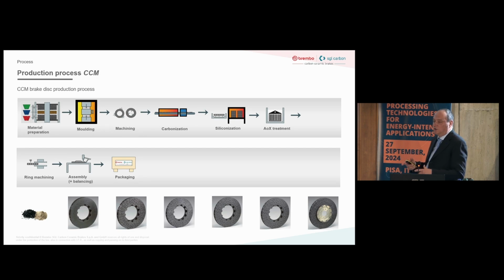So each type of rotor has the recipe for molding. Then after molding and easy machining, just making the holes, and then carbonization to transform phenolic resin into carbon, and then we have the carbon-carbon material that has to be infiltrated, so batch ovens for infiltration with the silicon, and then anti-ox treatment. As I said, we have surface fibers, and fibers with oxygen are burning, so we can reduce the burning of the fibers. And then the very easy and complex machining. Remember the DTV: here we have to obtain less than 20 microns by machining a composite. And then assembly and packaging.